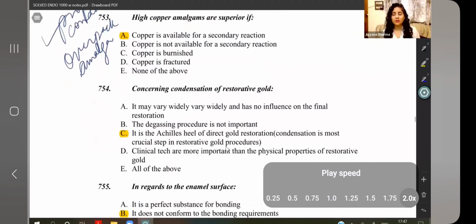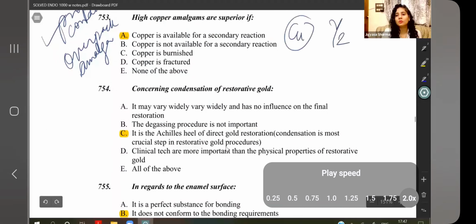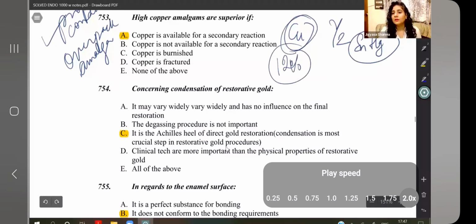High copper amalgams are superior. Now in the last class, I gave you the reaction of copper with amalgams. When you add copper to your amalgams, you eliminate the gamma 2, which is your tin mercury phase. When you add copper, more than 12%, which is your high copper, you eliminate the gamma 2 phase by forming the eta phase, which is your copper tin phase. So it eliminates the gamma 2, which is the weakest phase.